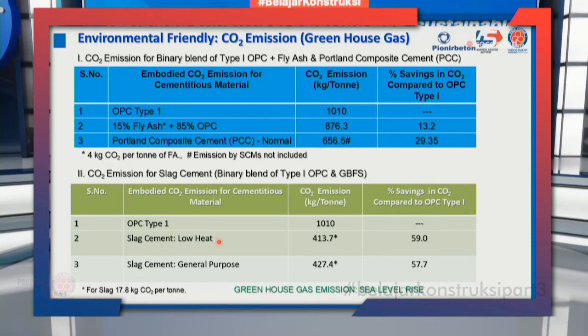Now I give you a comparison here. If I use OPC, and if I use a combination of 15% fly ash and balance OPC, and if I use Portland composite cement, which is PCC. So look at this column, if I replace OPC by a combination of 15% fly ash and 85% OPC, I save about 13.2% of carbon dioxide. The reduction is there, that much reduction. If I use Portland composite cement instead of OPC, I save almost 29%. It's a very good thing to publicize. You have done a good service to the entire humanity.